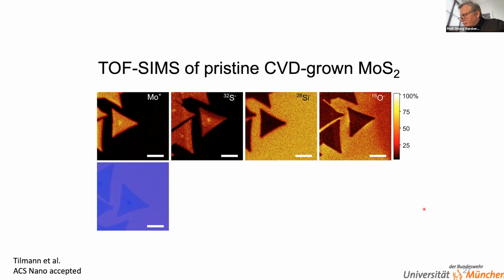We actually started to look with our TOF-SIMS a little bit closer into the counts. And this is now an example of the CVD grown material which has not been transferred. Something which I called earlier on nice and clean and very pristine. So this comes straight after growth at 700 degrees out of the furnace and into the machine, and this is the flakes we've been looking at.